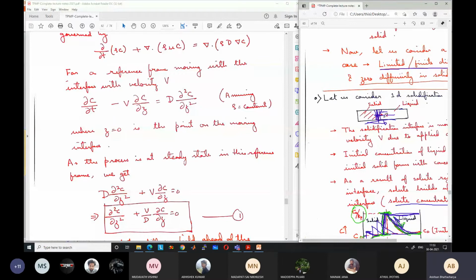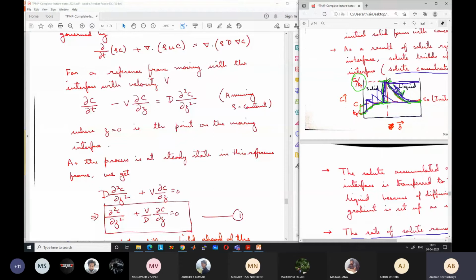If you go to another point also, you will exactly see the same thing: the solidification interface is at z equal to 0 and liquid is coming with velocity v and going out with certain velocity. And concentration also remains similar. So wherever you go, you will see that on your right hand side, the concentration gradient is like this, and on the left hand side, the concentration is like this. At this steady state, we are ignoring the far away part. So near the interface, the concentration in the solid is like this and the concentration in the liquid is like this. Always you will see this from the moving point. So the boundary layer remains steady if you are moving with the boundary layer.